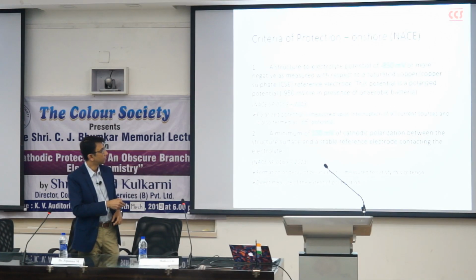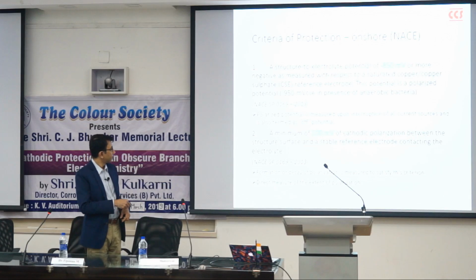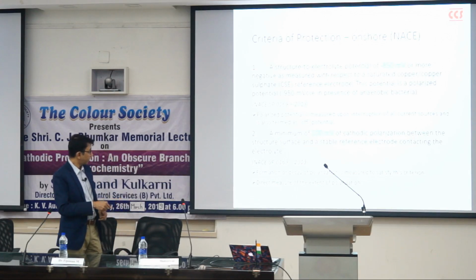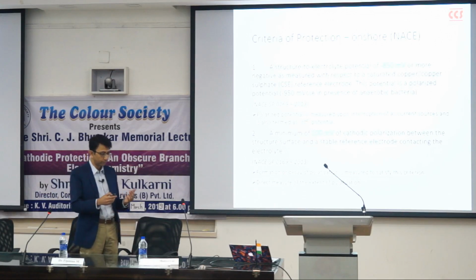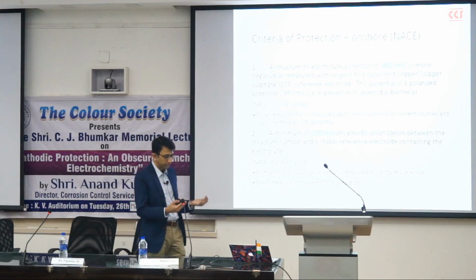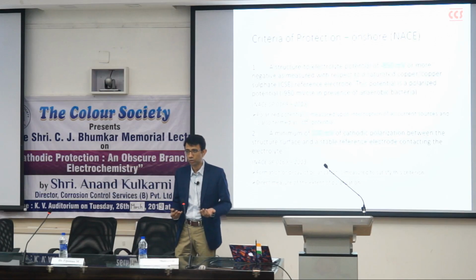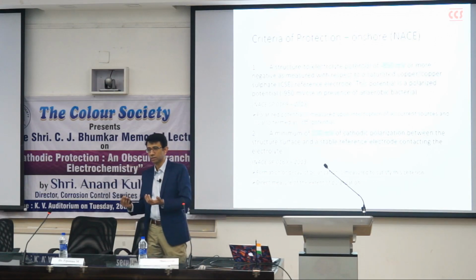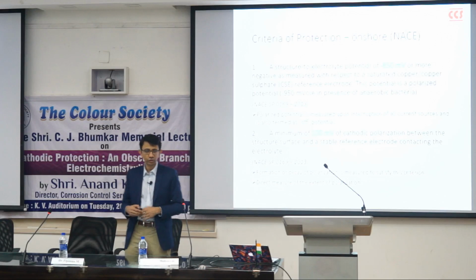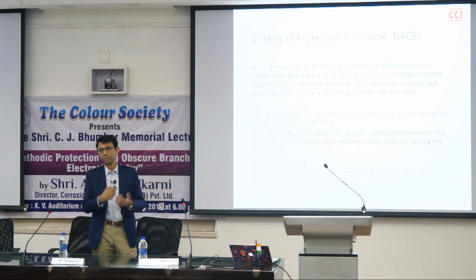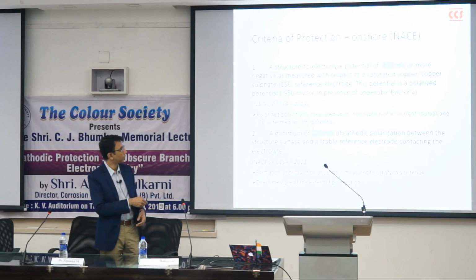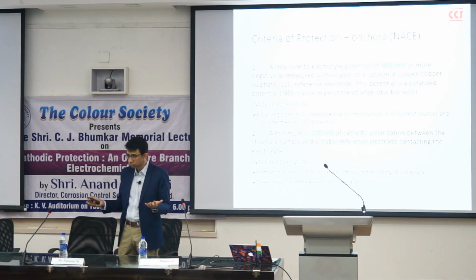And so this is the threshold of protection. Another criterion, which is a direct measure of the cathodic protection, is the 100 millivolt of cathodic polarization. So if we have a certain basic potential and we are able to polarize the structure negatively by at least 100 millivolts, and so we have a natural potential of say minus 600 millivolts. We polarize it and I get an off potential of minus 700 millivolts.